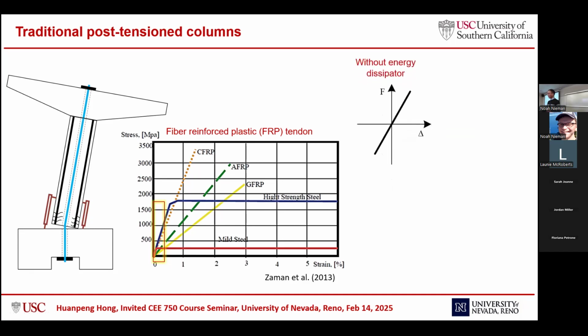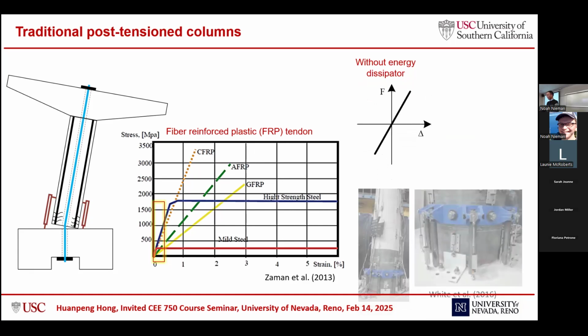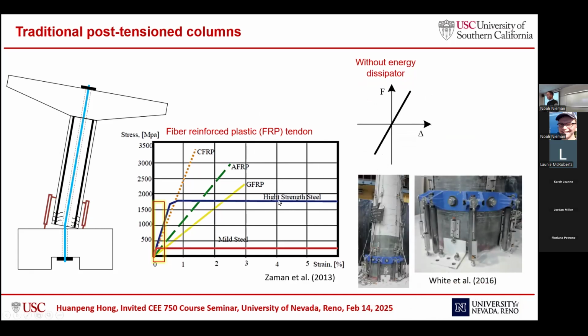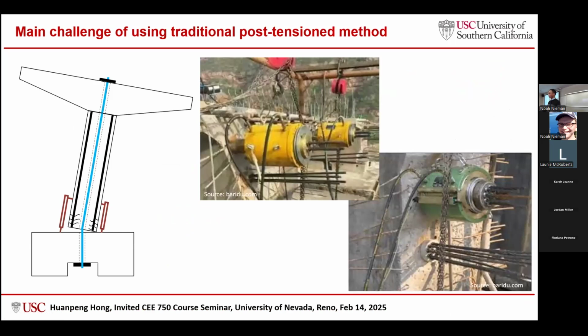And if we only use the elastic region, the force displacement curve of this column will behave like this: there's no energy dissipation from this material. So in addition to this FRP or high-strength steel tendon, we still need to add some energy dissipation elements, such as this brown part here. After adding the energy dissipators, the force displacement curve is what we want. And the main challenge of the traditional post-tensioning methods is that really heavy hydraulic devices are needed for on-site construction. This is unavoidable, so this is the main challenge of the traditional methods.